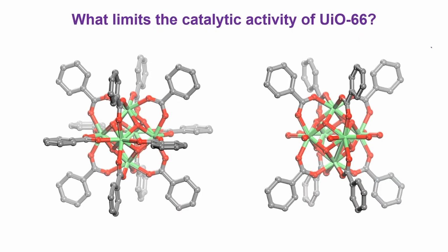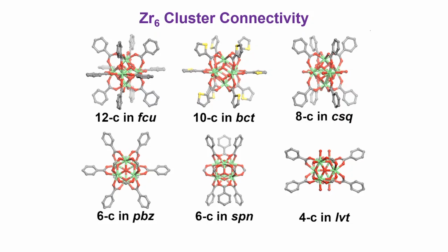Then how can we deal with this problem? You could start thinking about the first material we dealt with, the benzene dicarboxylic acid. The porosity is on the low end. Second, either we are relying on the surface or defects, or if we are not, a carboxylate has to come off for the simulant or the agent to bind for the catalysis to take place. However, if we go to lower connectivities, then you have the active site already ready for the reaction to take place. And in the field nowadays, you could make materials using linkers to dictate what node you make. And you could go from 12 connected all the way to 4 connected.